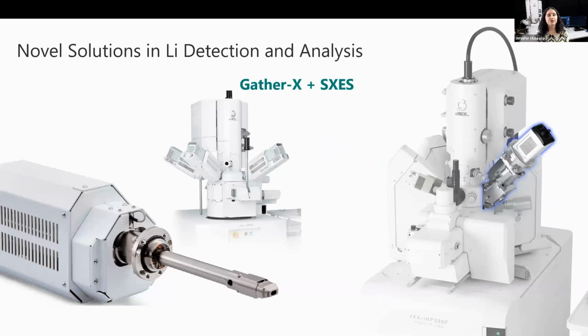So in summary, JEOL offers a comprehensive suite of solutions for the analysis of lithium-ion battery materials. The Gather-X Windowless EDS detector delivers a highly intuitive user experience and offers enhanced sensitivity at low accelerating voltages while also supporting high voltage analysis. Its high spatial resolution enables precise elemental mapping of sub 20 nanometer particles and thin surface layers. The Soft X-ray Emission Spectrometer provides detailed chemical state analysis and is capable of detecting light elements such as lithium and boron at concentrations as low as 100 to 200 ppm.